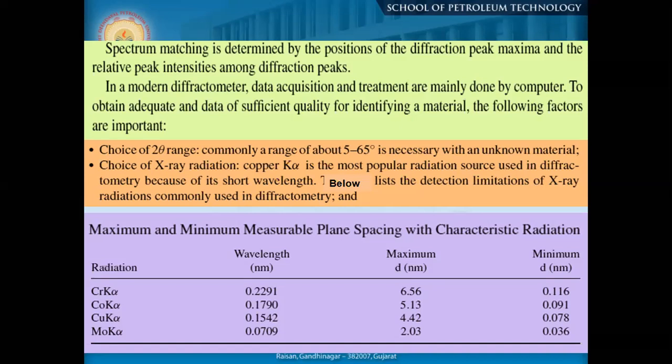Commonly, a range of 5 degrees to 65 degrees is necessary when working with an unknown material. I told you, if you go below 5 degrees, you may get certain problems, because at less than 5 degrees you require really dense data. That means the step size should be very small.